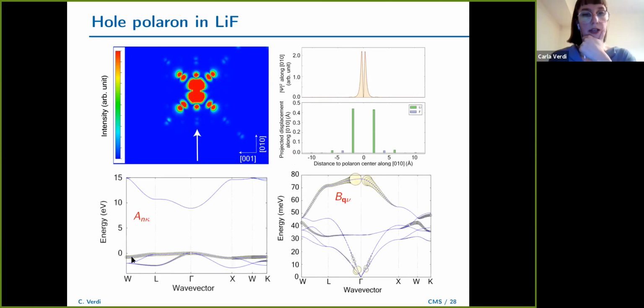Now you can see that the electronic states that are involved in this polaron are all states at the top of the valence band, and the phonons that interact with the electron are mainly, again, the longitudinal optical phonons, and mainly at short wavelengths, sorry, large wavelengths. So this is what in the literature people would call a Holstein polaron. So it's not simply the parabolic band, but it's a flat band interacting with long-range optical phonons. Again, we didn't discover this because we made an a priori model. We discovered this by doing fully first principles calculations.